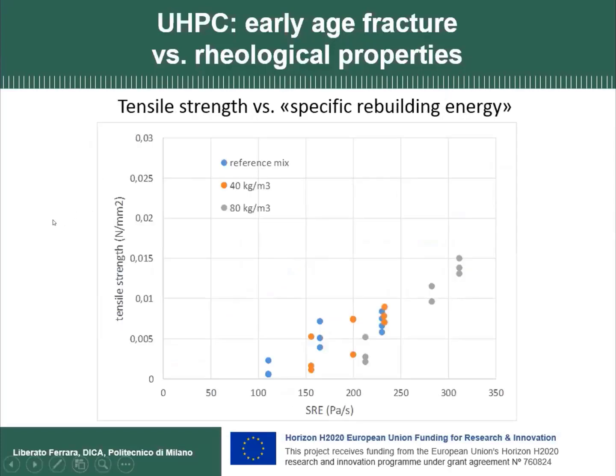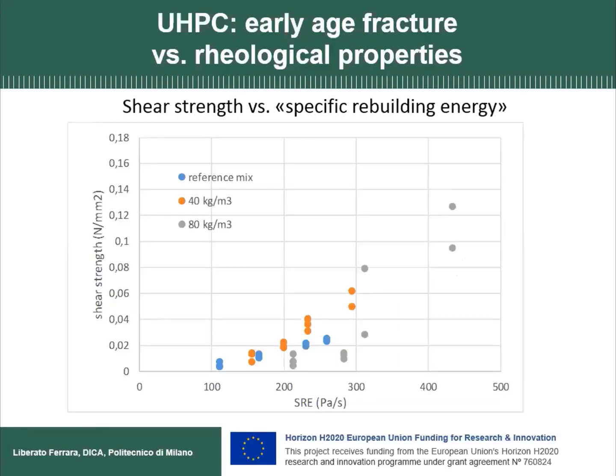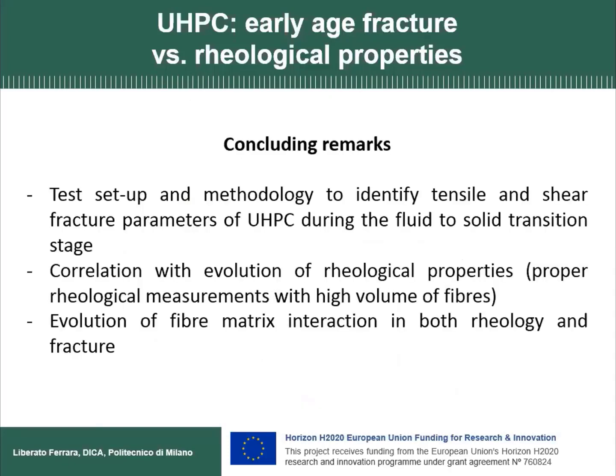So what we did here, we plotted the mechanical properties of the mix, so the tensile strength, versus this structural specific rebuilding energy. Obviously, these refer to the same time frame, but for the different mixes, you have different values. And you can see that there is a good trend, clearly highlighting how this thixotropic structural rebuilding starts being responsible for the mechanical properties, both for tensile strength and for shear strength that we have been measuring with our device.